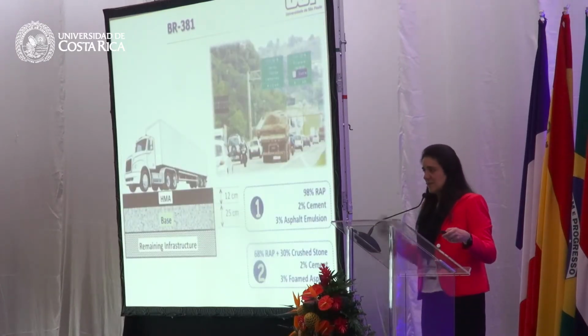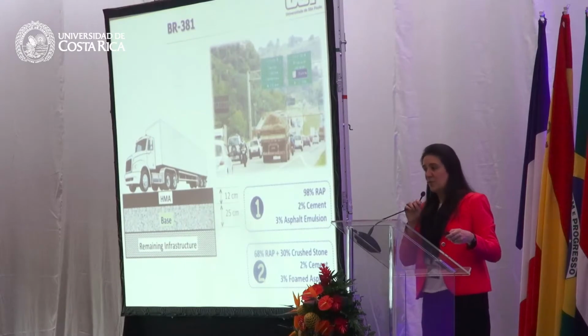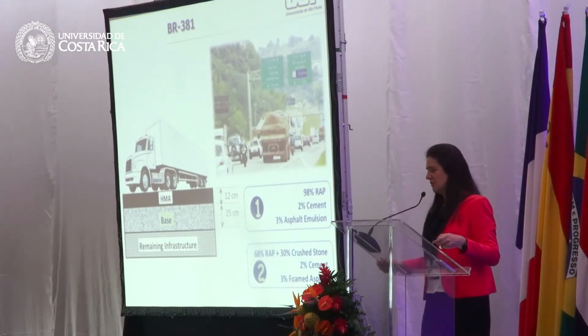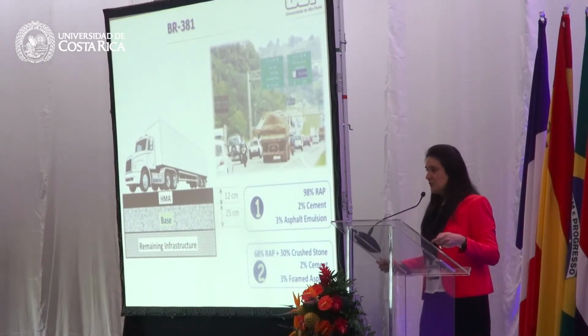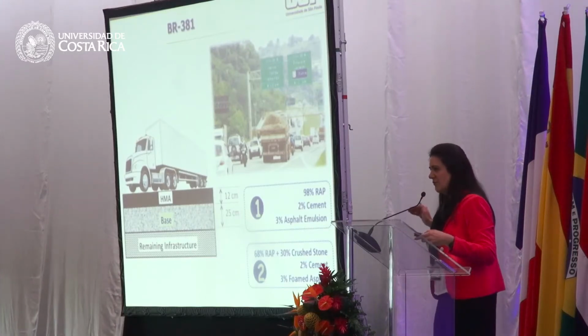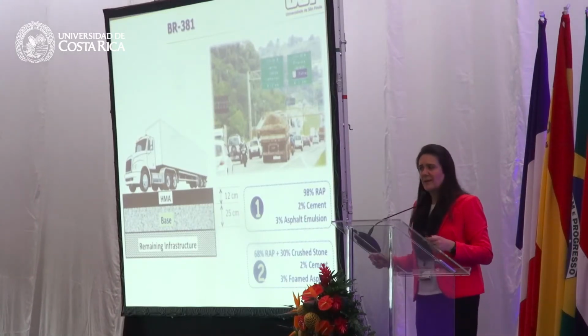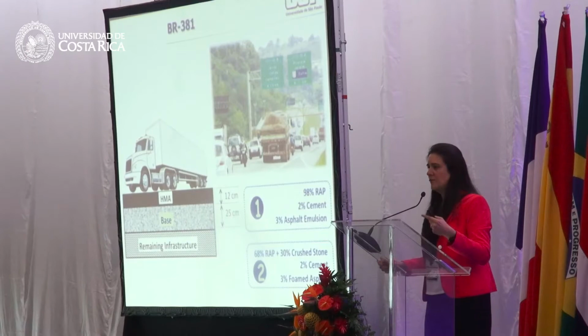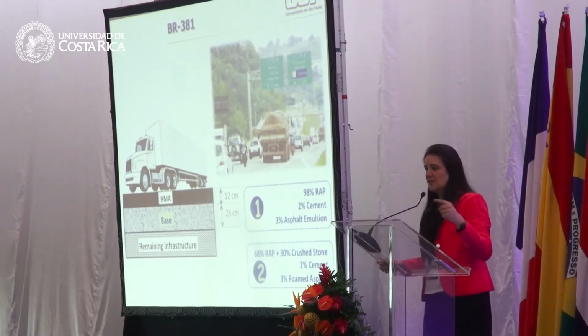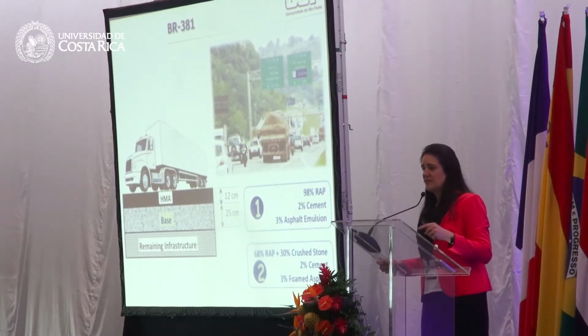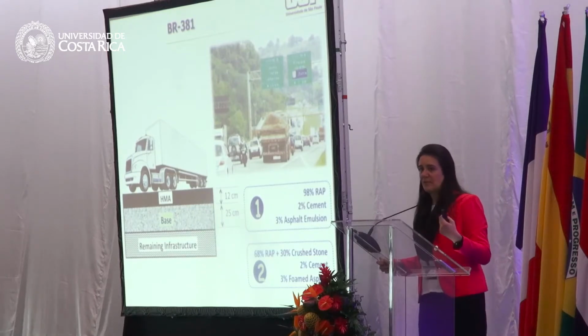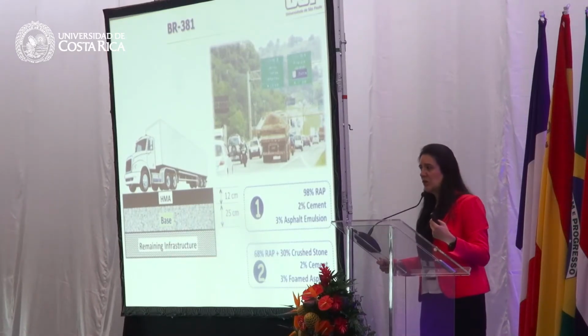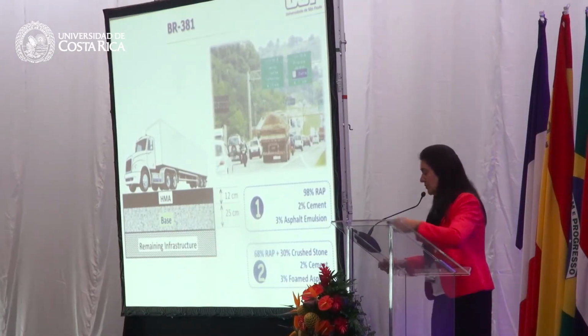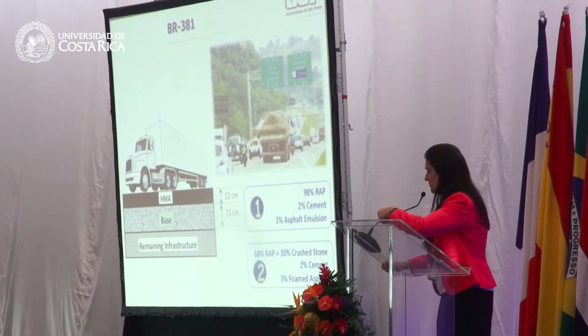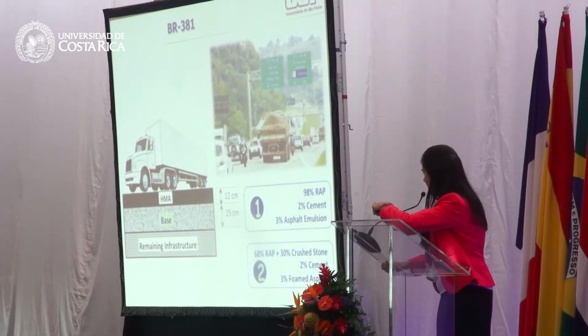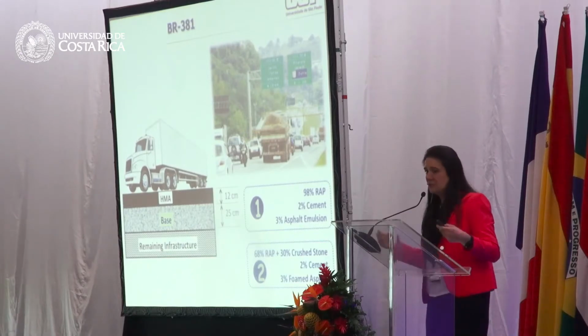The other job site, we compared the foam with the asphalt emulsion. If you check the composition of both, you may ask, oh, why in just one you've put new aggregates? Because in the foamed process, I need the fines, and the RAP didn't give me the necessary amount of fines. So we've put on the mix number 2, that is the foamed one, 30% of new crushed stone.